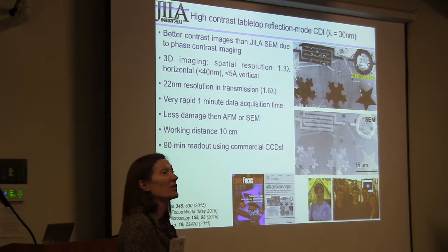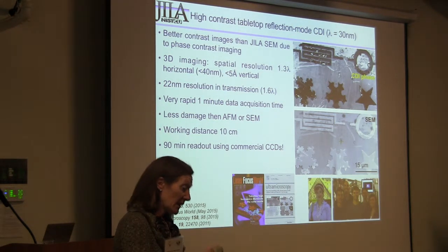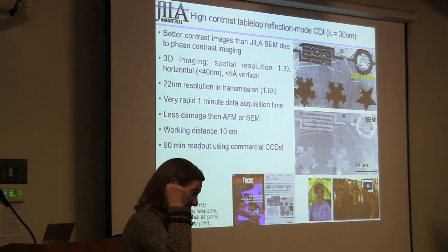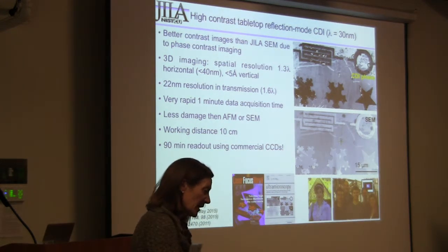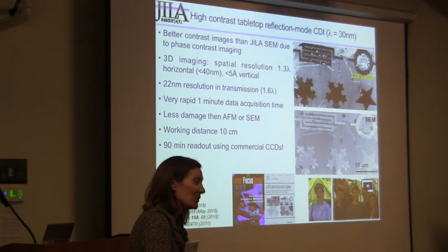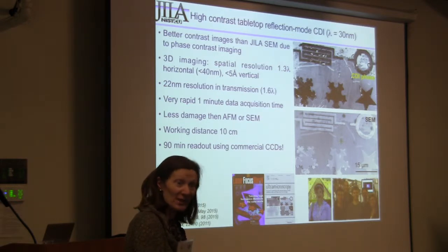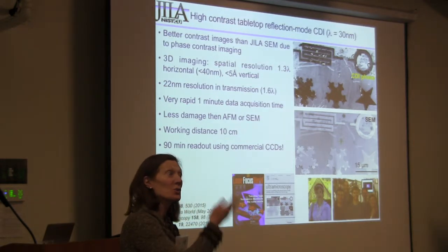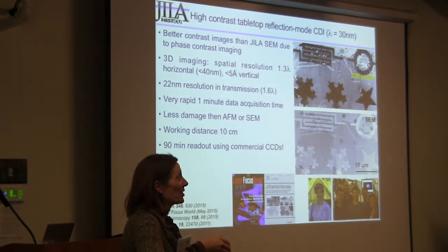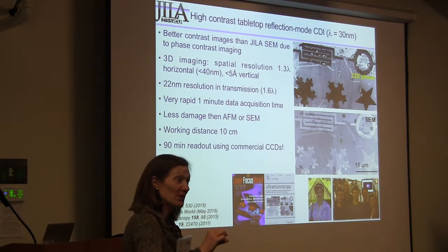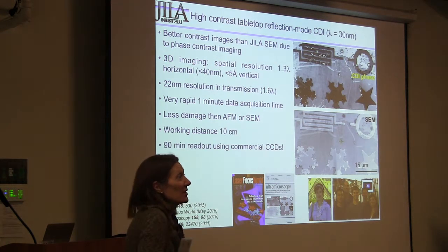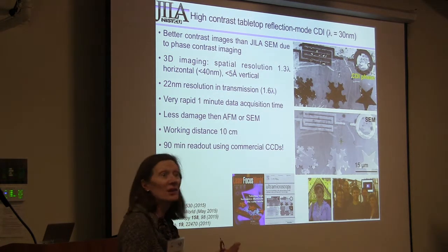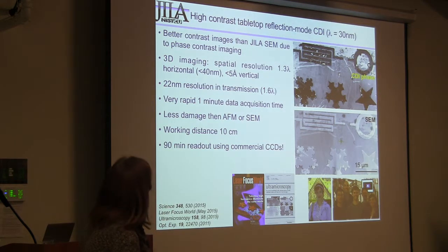And this is just because of the contrast mechanisms. In an electron microscope, if you're firing your electrons at the sample, then you're relying on a different amplitude of reflection from the sample. That's your contrast mechanism. Whereas with the harmonics, the contrast is a tiny path difference due to a profile change on the surface, and of course it's shorter wavelength light, so you get really, really high sensitivity.